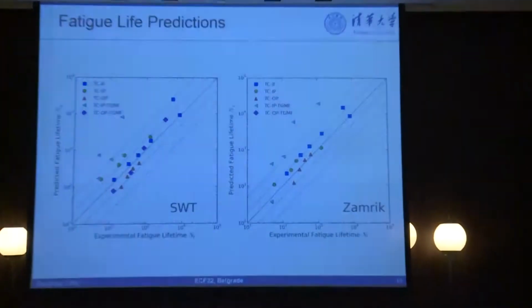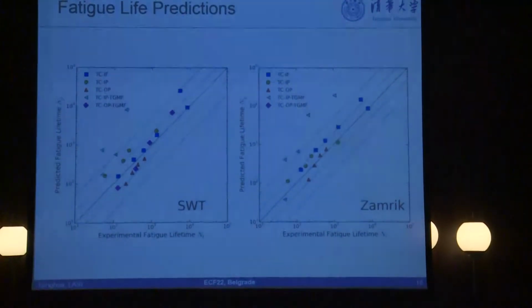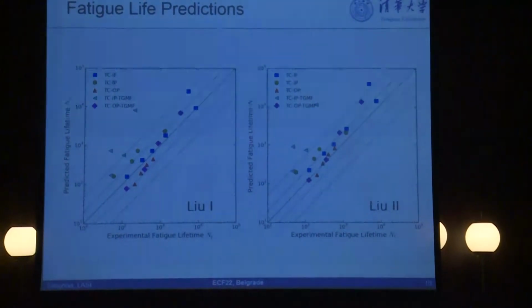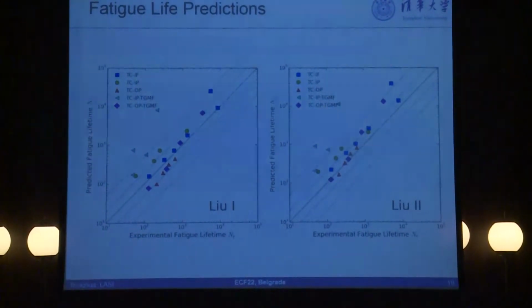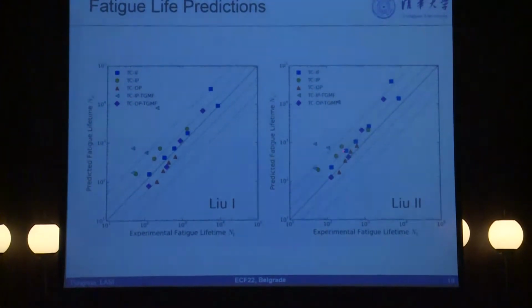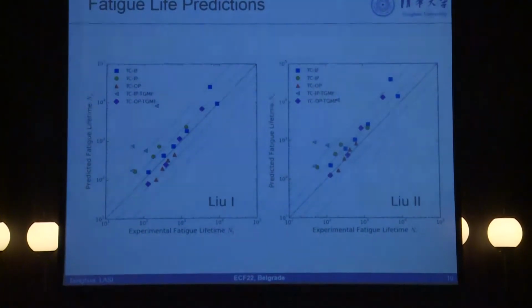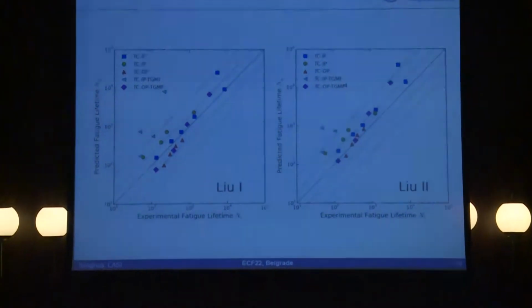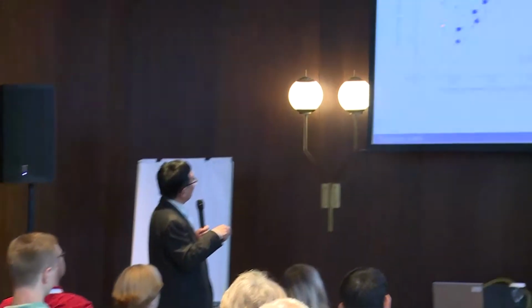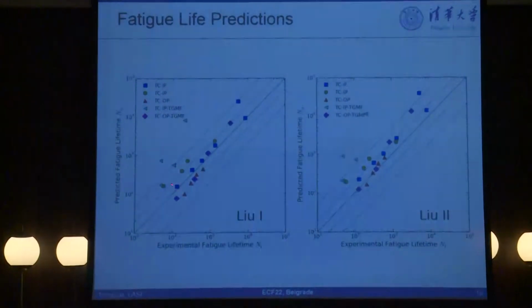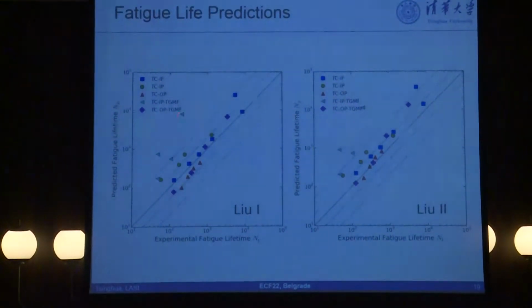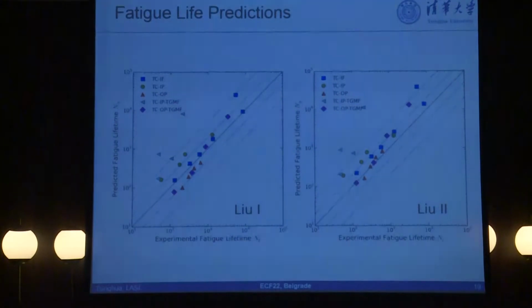And you see a similar situation, rather large scattering, and the Liu model parameters present the best approximation. You see the scattering of Liu model 2 is not so large, and of Liu model 1 is not so large either. That is the double line, that is the 5-times line, and okay, that is more or less up to 2 points. The rest are within this 5-times line region.